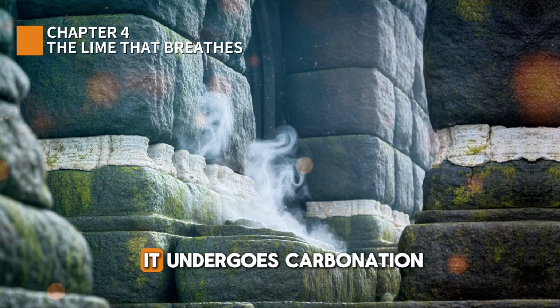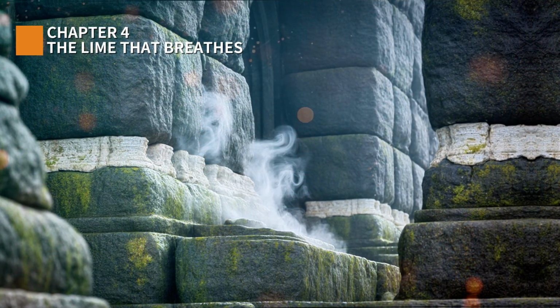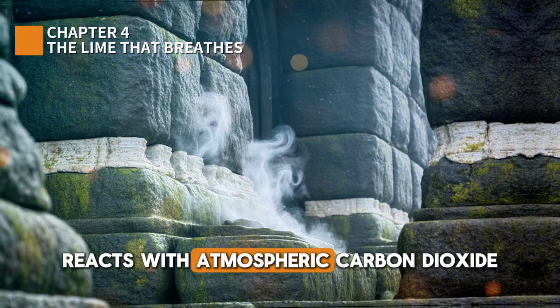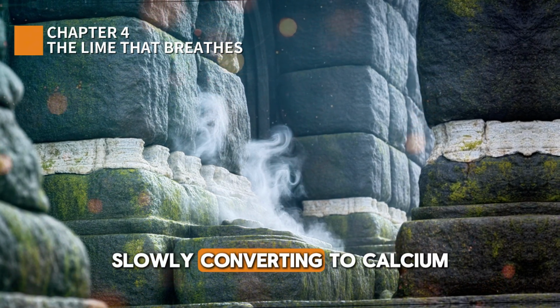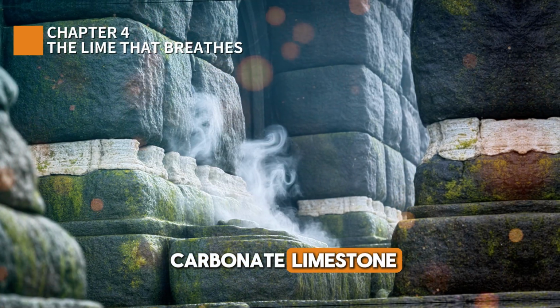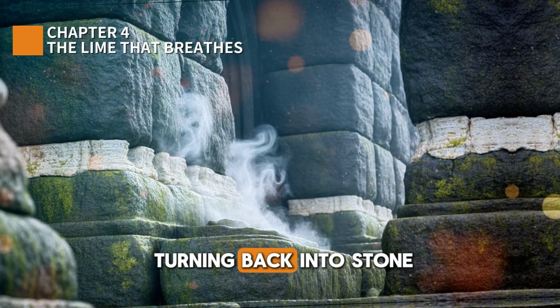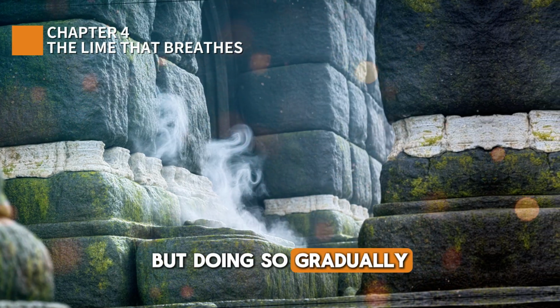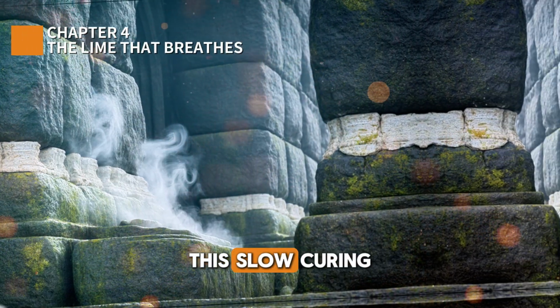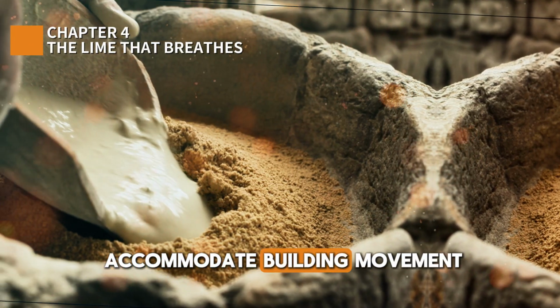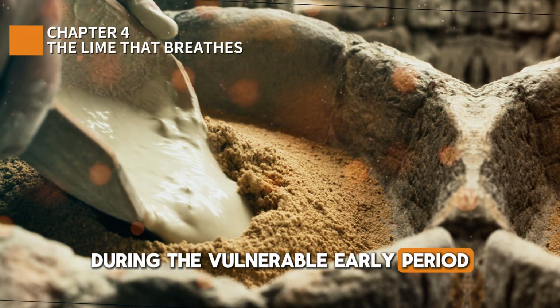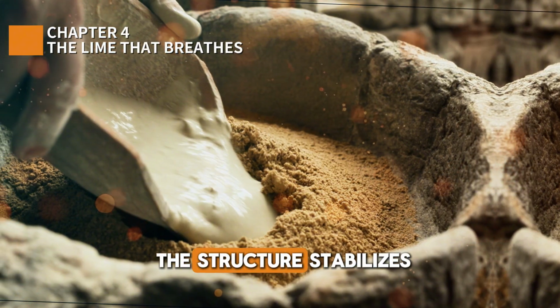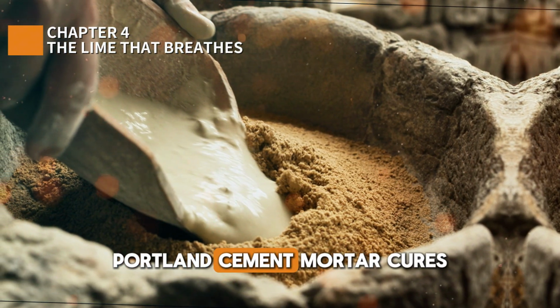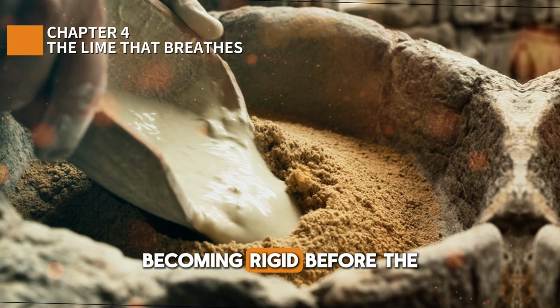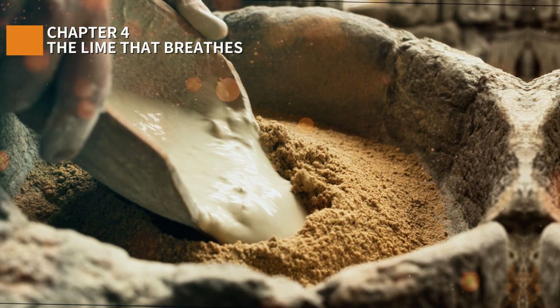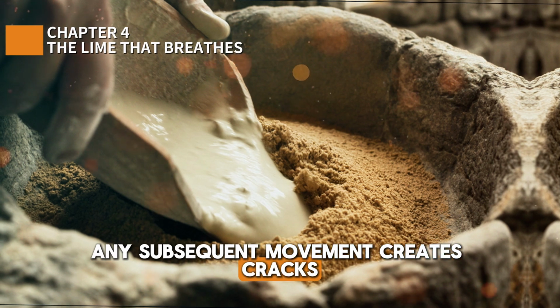As lime mortar ages, it undergoes carbonation. Calcium hydroxide reacts with atmospheric carbon dioxide, slowly converting to calcium carbonate, limestone. The mortar is literally turning back into stone, but doing so gradually over decades or centuries. This slow curing allows the mortar to accommodate building movement during the vulnerable early period, then gradually strengthen as the structure stabilizes. Portland cement mortar cures in weeks, becoming rigid before the building has fully settled. Any subsequent movement creates cracks.